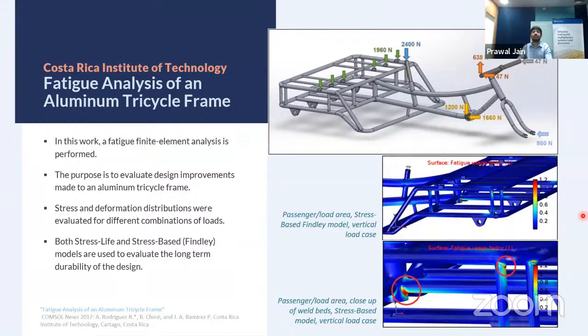And then a fatigue analysis was carried out by comparing the stress levels present in the structure to the fatigue limit of the aluminum material. And this result revealed that the long-term durability of the design is compromised. For this reason, additional fatigue simulations were developed in order to improve the design of the tricycle. To do this, they used COMSOL Multiphysics, where they worked with S-N curves for the material to better evaluate the number of cycles the structure might handle before the fatigue crack appears, or some part of the tricycle fails.